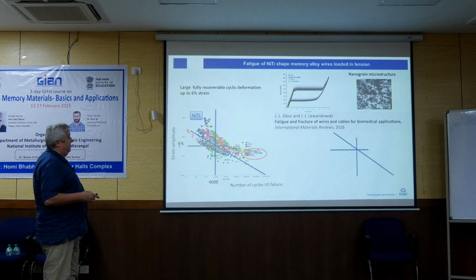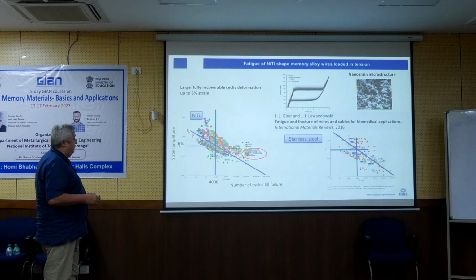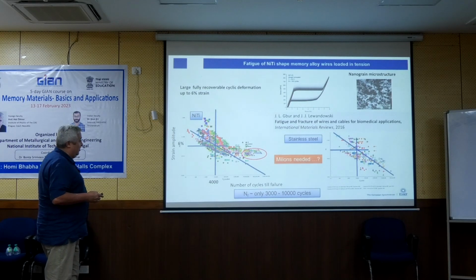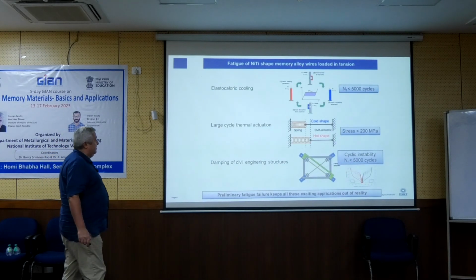I searched in the literature whether there is some difference between nitinol and steel, for example. This is from a very nice review article, Fatigue and Fracture of Wires and Cables for Biomedical Applications, where one can compare the overview of the fatigue data from stainless steel and nitinol. You find that for a similar amplitude, even though 6% for nitinol is almost acceptable, 6% is definitely not acceptable for steel. But still, the spread of the data and these curves are kind of similar. So the review of the literature said it probably doesn't play much role.